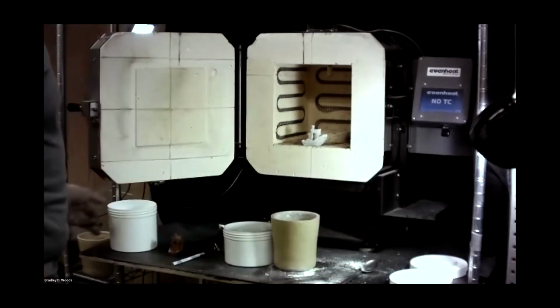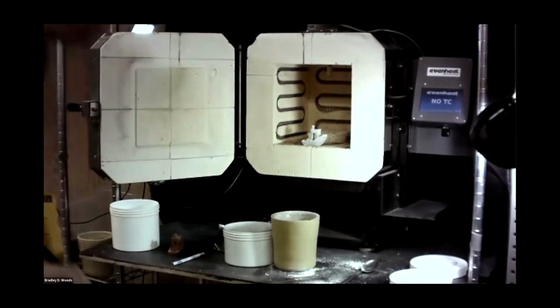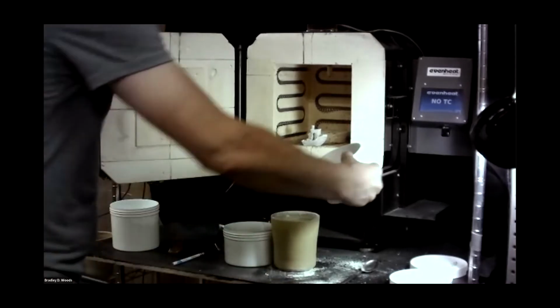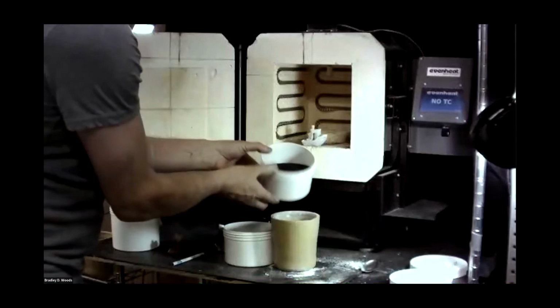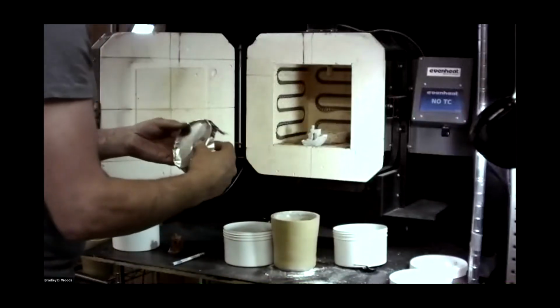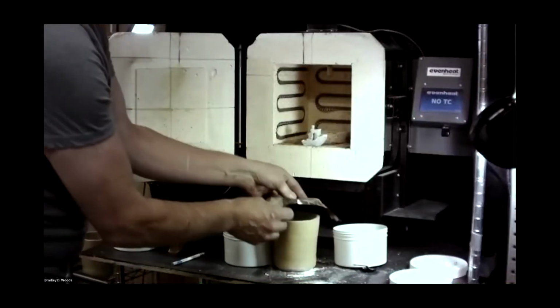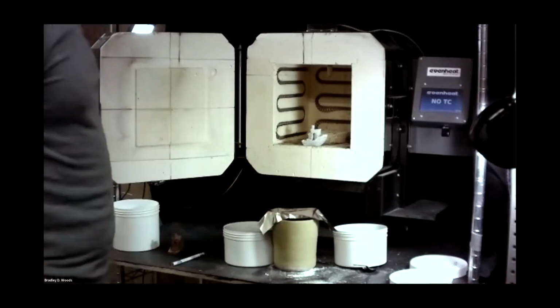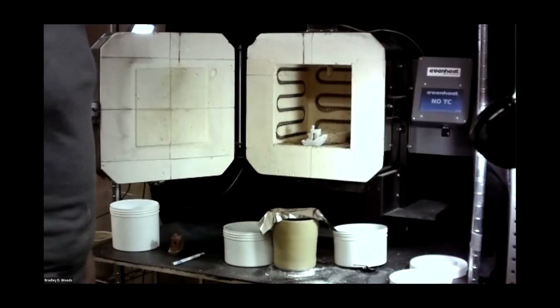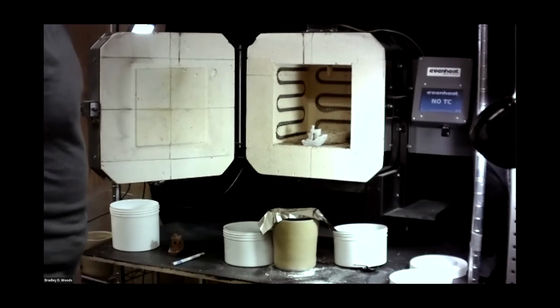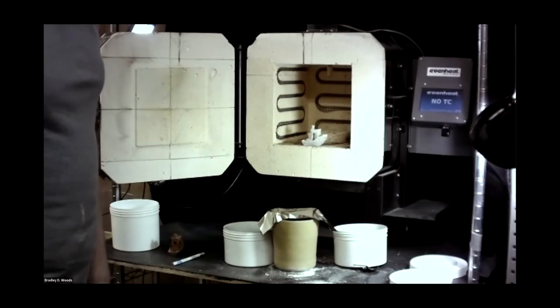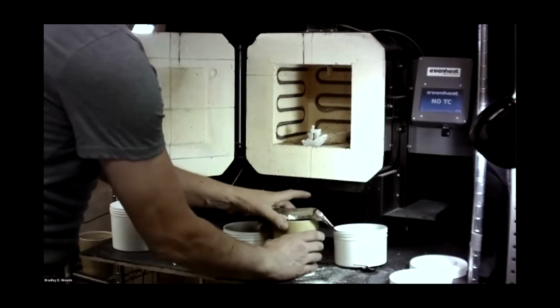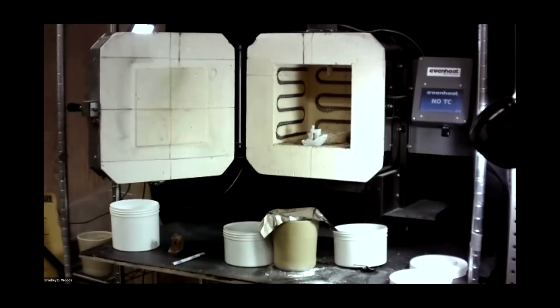We would put our part in. We fill it the rest of the way up. We put some sintering carbon on top of that. Cover it a little more lightly. We want the gases to be able to escape easily. So you can cover it like that, and it'll save you some of the carbon. But otherwise, it's the same process. This is more of a one-step process. You're loading the kiln completely, including the sintering carbon, the crucible, before you put the crucible into the kiln.